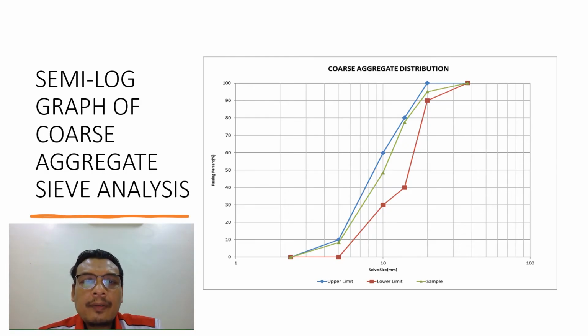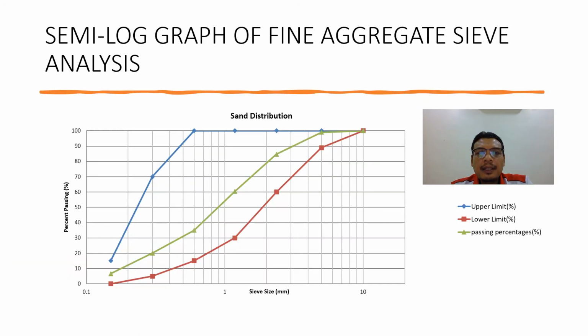This is the result of the semi-log graph of coarse aggregate sieve analysis that is illustrated. Based on the results shown, a sample of coarse aggregate in all sizes is within the limitation and acceptable in mixing of the concrete. This is the result of the semi-log graph of fine aggregate sieve analysis that's illustrated. Based on the results shown, fine aggregate in all sizes was seen within the limitation and considered appropriate material in the concrete mix.